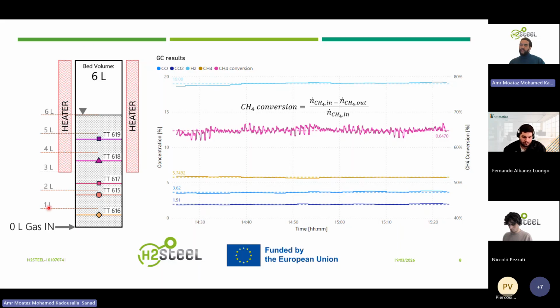On the left-hand side instead, we have a schematic for the reactor with the position of the multi-point thermocouple, the different temperature sensors that can also monitor the temperature within the reactor itself. It is evident, however, from the results of this test shown on the right-hand side in this graph that the steady state conditions can be achieved after, of course, a transition state, but eventually the steady state is achieved and is maintained for more than an hour.